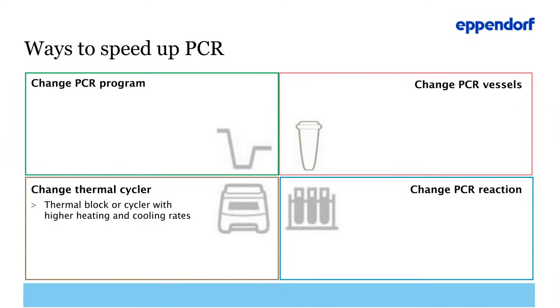Now, the second strategy is to use thermal blocks or thermocyclers with higher speed. For example, the choice of thermal block material is between higher ramp rates or better temperature homogeneity. We know that silver blocks are faster than aluminum blocks, but aluminum block is better at temperature control and hence has relatively better overall temperature performance.